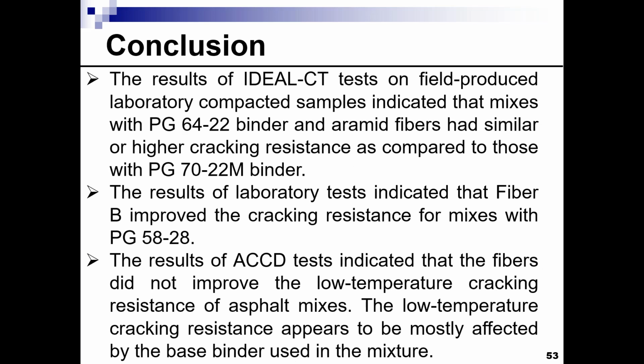Now, if we go to the IDEAL-CT, on the field produced tests, we're seeing that in general, whether it is the city of Columbus or the city of Kettering, a PG 64-22 with an Aramid fiber seems to have a similar or higher cracking resistance as compared to the polymer modified. And again, that is based on the IDEAL-CT. The results also indicated that fiber B improved the cracking resistance of mixes with a PG 58-28.